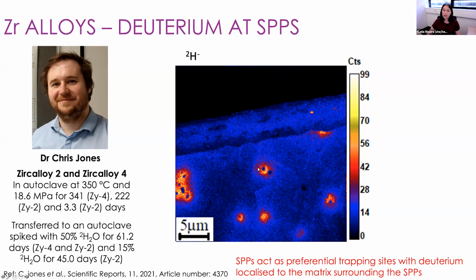And this is important because we're really interested in looking at deuterium pickup into zirconium alloys, and this had not been observed previously. If we're really interested in knowing where the hydrogen is segregating to in these zirconium alloys, we need to have a full picture before these alloys go into service. This had not been observed previously, and I think this comes down to being able to look at a large area with the NanoSIMS compared to other techniques such as atom probe and TEM.